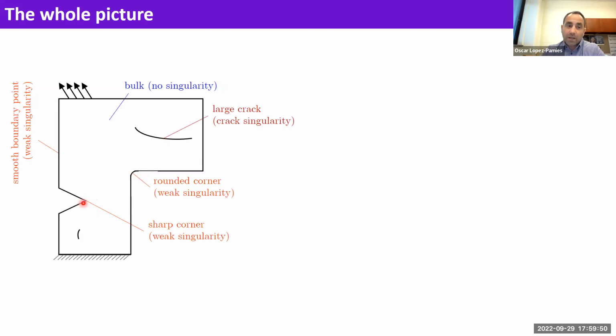And you may nucleate a crack from there, or you may have a rounded corner, which is not sharp, but the geometry is changing very rapidly, and you also may nucleate from there, or you may nucleate from the boundary that is smooth, right? All these things have been observed to happen. So what we now need to think about is, when we think about fracture nucleation, how do we describe the entire picture? How do we account for the fact that nucleation of fracture can take place in many different ways?